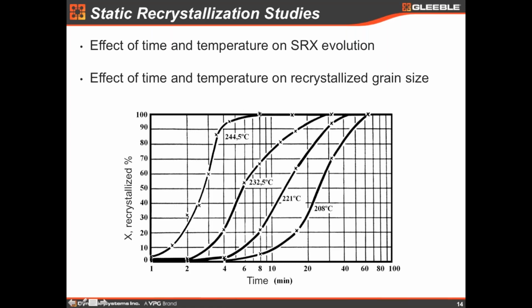I think the advantage of using the Gleeble is that you have uniform temperature across the cross section of the specimen. So you can rely on what you see in the microscope. So if you see close to the surface of the specimen, you can see a different microstructure as compared to the center of the specimen. It doesn't happen at the Gleeble.